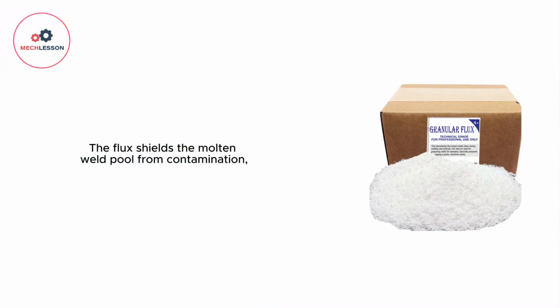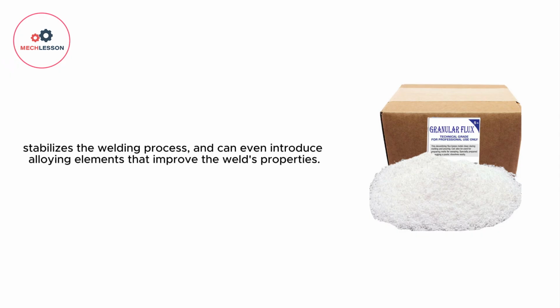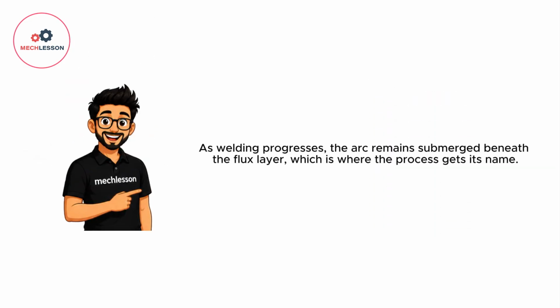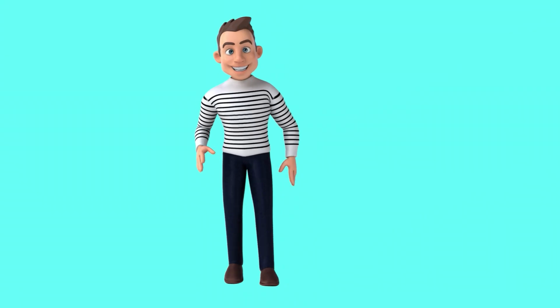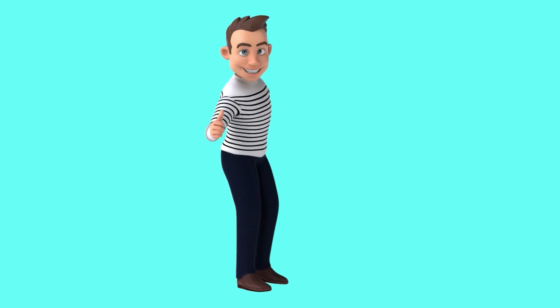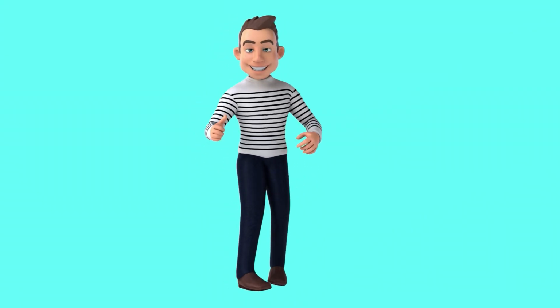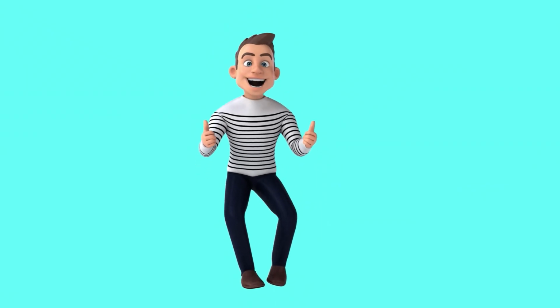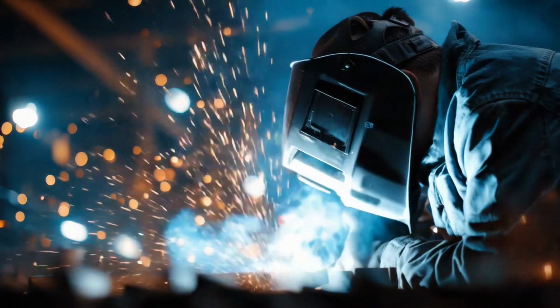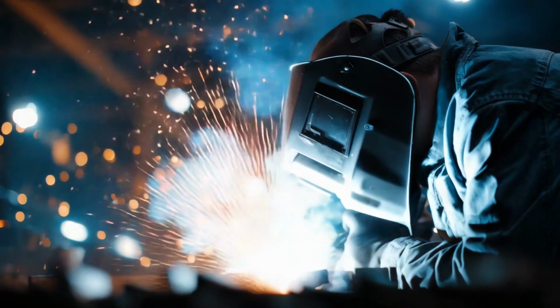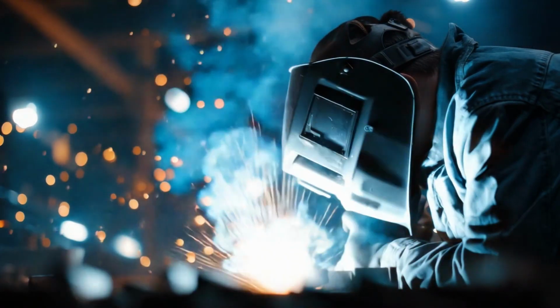The flux shields the molten weld pool from contamination, stabilizes the welding process, and can even introduce alloying elements that improve the weld's properties. As welding progresses, the arc remains submerged beneath the flux layer, which is where the process gets its name. The result is a highly efficient welding method capable of producing deep penetration, smooth weld beads, and extremely high deposition rates. In fact, few welding processes can compete with SAW when it comes to productivity.